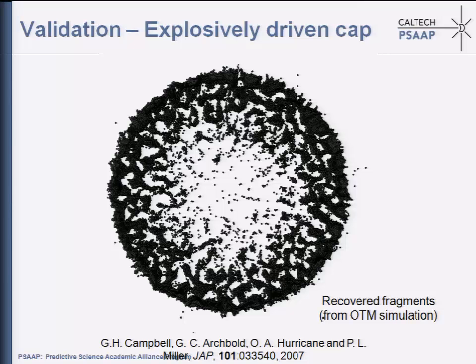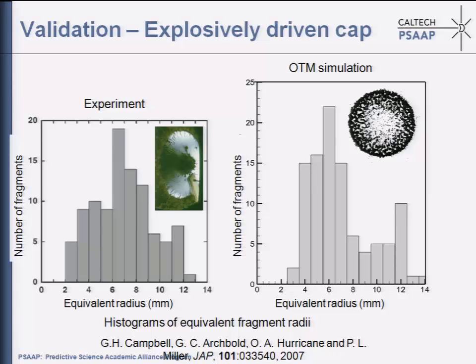And so now we can put together histograms of fragment size, and I can compare with the ones that were measured experimentally. Here you have the experiment: this is the size of the fragments and this is the number of recovered fragments. And here you have the fragment size from the calculations and the number of recovered fragments.